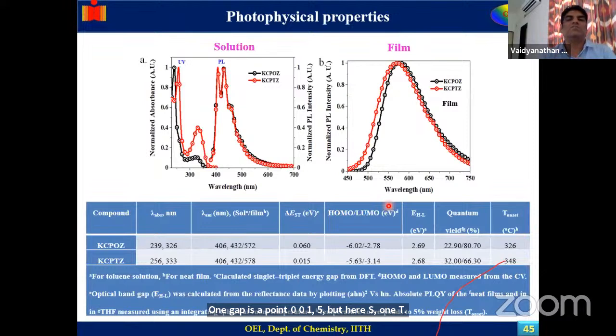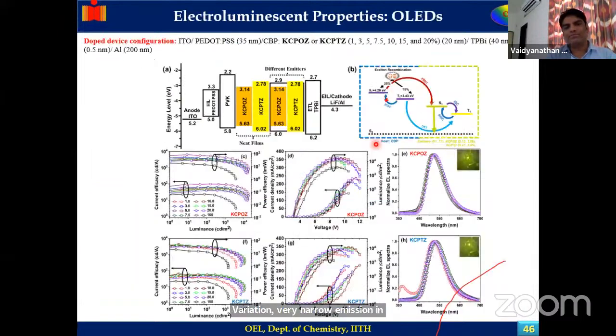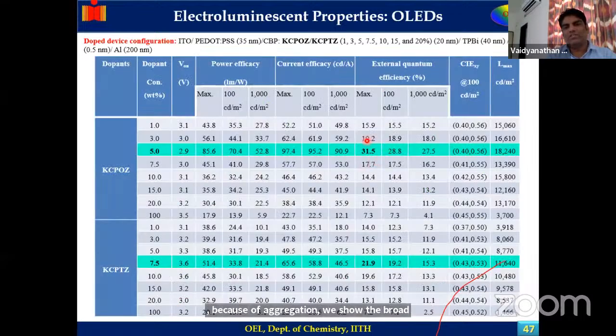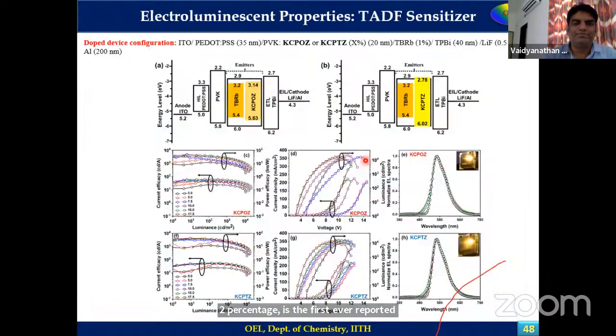In solution and thin film, it's showing some variation: very narrow emission in solution, while in thin film, because of aggregation, we see broad emission. Making the device, we found external quantum efficiencies of 31% and 22% in the case of phenothiazine and phenoxazine. This 32% is the first ever reported in solution process. They're trying to make a patent out of this compound.